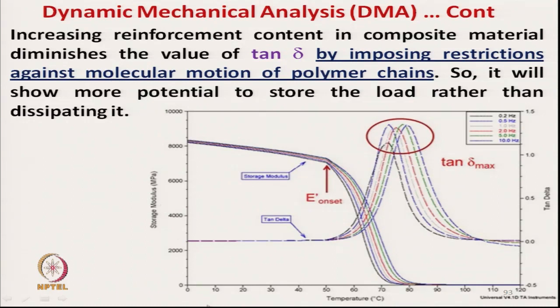But if we increase the temperature, as this picture shows, at lower temperature the storage modulus was high, but once we increase the temperature, the storage modulus suddenly drops after a certain point, the E dash onset. So, it starts dropping, which means viscous flow is occurring. On the other hand, as we increase the temperature, the damping behavior, the tan delta, increases and reaches a maximum value.